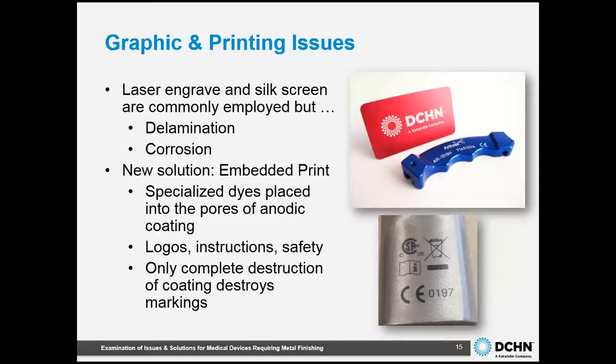Well, let's start with silkscreen, which is applied on top of the anodic coating. Changes in temperature can cause contraction and expansion of the base metal and can cause delamination of the silkscreen and make the graphics unreadable. Also, chemical attack can loosen the bond between the screen and the substrate. Laser engraving, while seemingly a better choice, will compromise the coating itself that is already easily damaged by the aggressive chemistries discussed earlier. This area of engraving is the first place of attack when exposed to harsh chemistry. And again, once that attack happens, it increases exponentially.